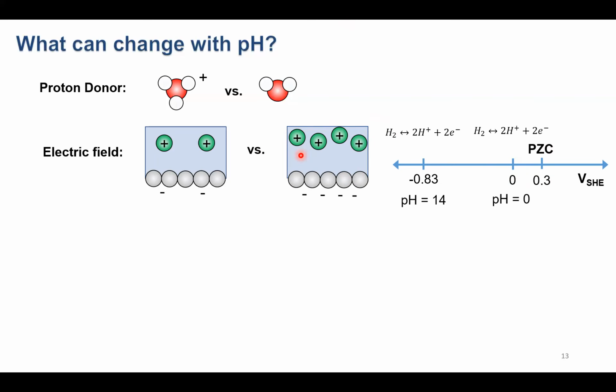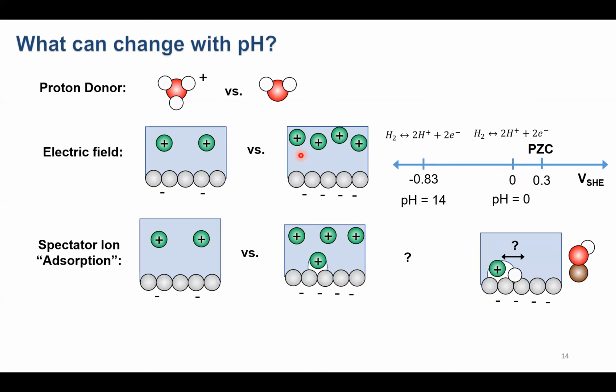Similarly, we might also ask, if we have this high concentration of cations close to the surface, could they also somehow affect reaction kinetics, separately from the electric field effects? Could it become favorable, when we have this high cation concentration at high pH, for some small fraction of these cations to sit close enough to the surface that they give up some of their solvation? We're going to call this, for now, ion or cation adsorption, but we'll talk more about what this really means later on. We don't necessarily need electron transfer. We're just saying they sit close enough to the surface to give up some of their solvation.